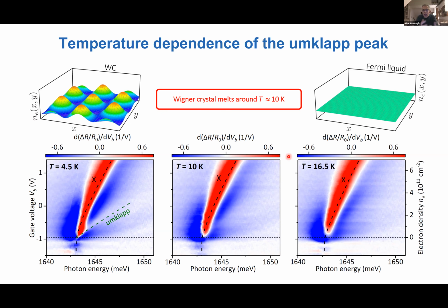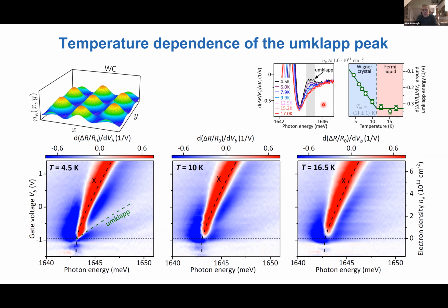Okay, so even though the actual exciton line hardly gets modified in terms of energy shift and line broadening, the Umklapp resonance disappears. And this is what we would expect, it's kind of consistent with the Lindemann criterion within a factor of 2. And so it looks like there is a transition from a Wigner crystal at low temperatures, or state with Wigner crystallites, to a Fermi liquid, although we really cannot say much about what's happening in between, which is the most interesting problem in this case.